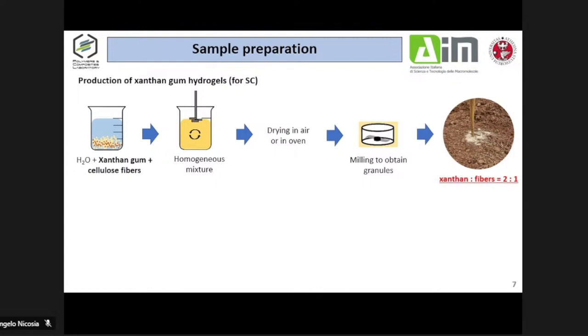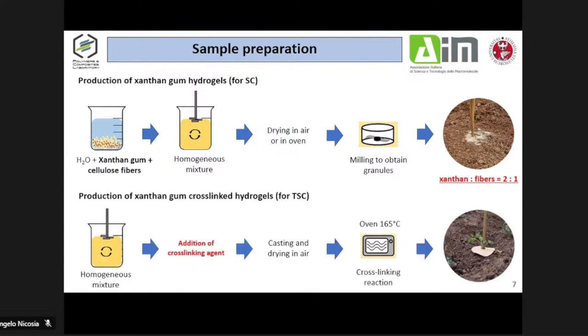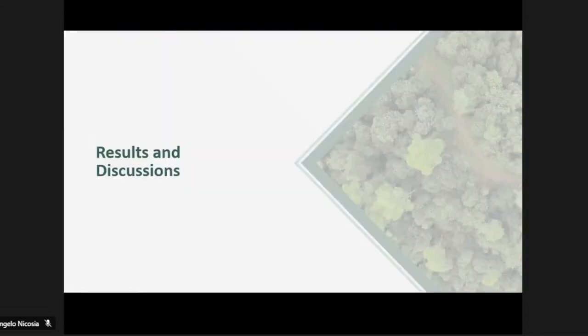For the topsoil cover, starting from the same mixture, we found the importance of adding a cross-linking agent, because after thermal treatment in an oven, we have a material which is stable in water. So when it rains, it doesn't dissolve, but remains there with a certain consistency and shape. Now I report just very briefly the results, mostly the practical ones.